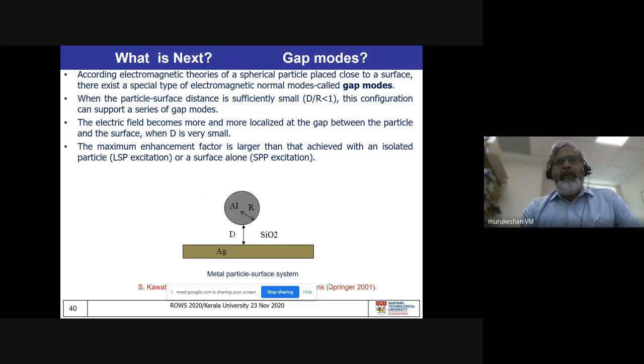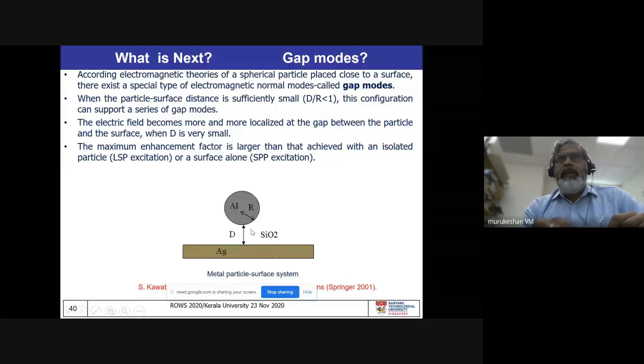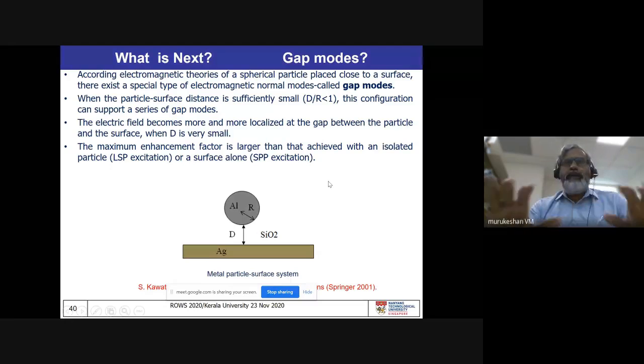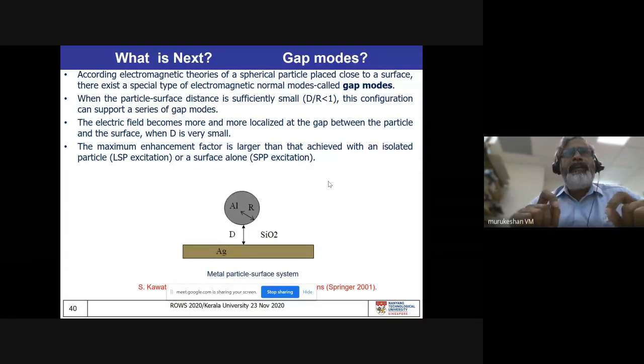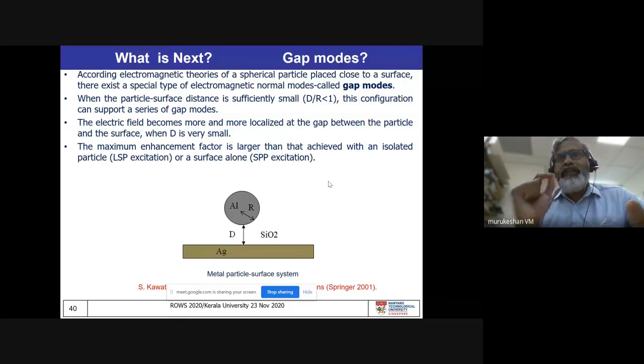Now, this is actually the work of Kawata. In 2001 to 2003, he did a lot of interesting work. What you need to do is bring this nanosphere, a nanoparticle, close to the metal surface. If R is the radius of the nanosphere, and D is the distance between the metallic surface and the sphere, and you can control the ratio D by R to be less than or equal to 1, there is a lot of theory there. What you can get is that you are able to observe very interesting modes, called electromagnetic normal modes. These are known as gap modes.